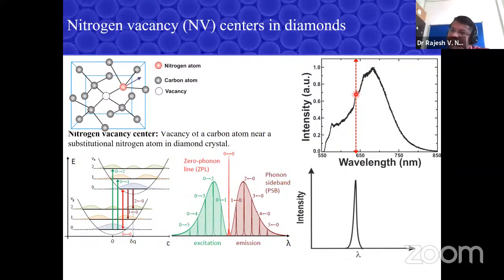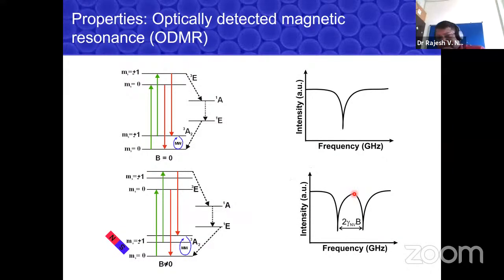It's very feeble. And if you can avoid all these vibration induced, all these phonon induced transitions, and clean up the system, and you have only this one single spectra which emitted the zero phonon line, which is a pure electronic transition, that's a good thing to start with in this system. So the whole effort of quantum photonics using NV centers is primarily focused on isolating the zero phonon line and suppressing all those other things.